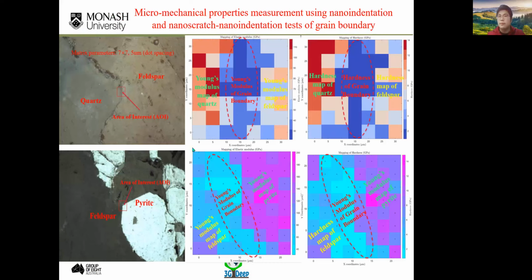Apart from that, we also carry out nano-indentation to obtain the mechanical parameters near the grain boundary and in the grain boundaries. And we found that both Young's modulus and hardness of the grain boundary is about 1/5 of the average value of the two phases.